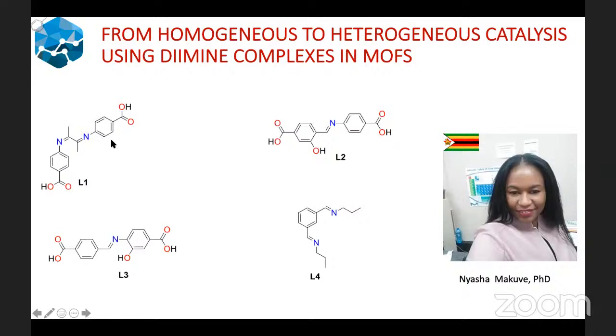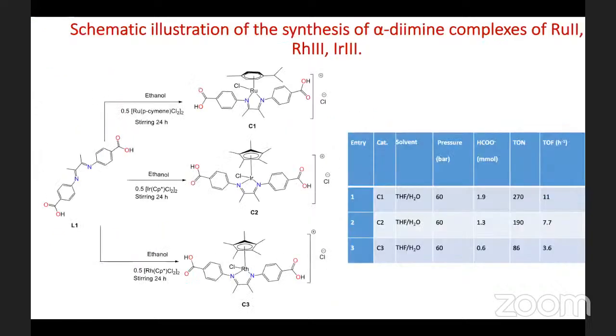So Nyasha managed to isolate a number of complexes. As you can see, these complexes have some carboxylic acid functionalities, which then allows them to be used as ligands in MOF synthesis. And then what she did was to form these diimine complexes of ruthenium using one of the ligands.